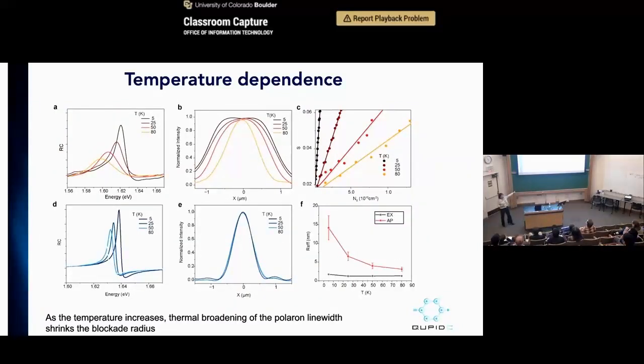And those measurements are, again, done at 4K. And what happens if you increase temperature, then you increase the line width of the polarons, and so the interaction you would need would be much stronger to create this blockade. So at higher temperature, you will see the shrinking of the blockade significantly for the polarons.